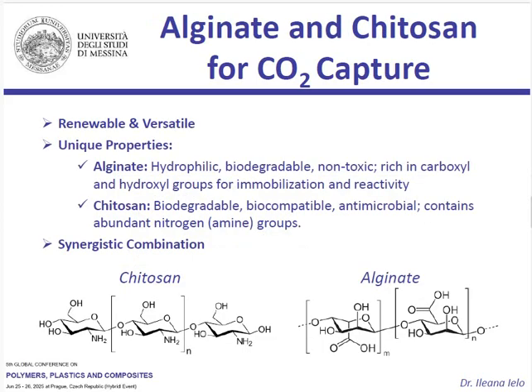These biopolymers, in particular alginate and chitosan, possess unique properties that make them ideal for CO2 capture. Alginate is a hydrophilic, biodegradable and non-toxic polysaccharide characterized by abundant carboxyl and hydroxyl groups, which are key for chemical reactivity and material fabrication. Chitosan, on the other hand, is known for being biodegradable, biocompatible, and for its antimicrobial properties. Crucially, it contains numerous nitrogen-containing amine groups.